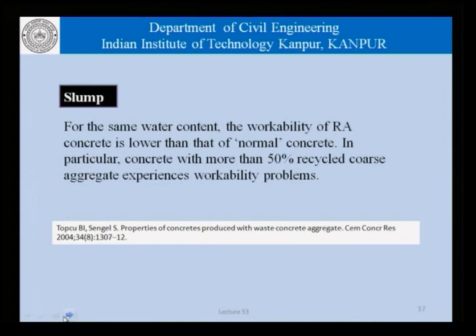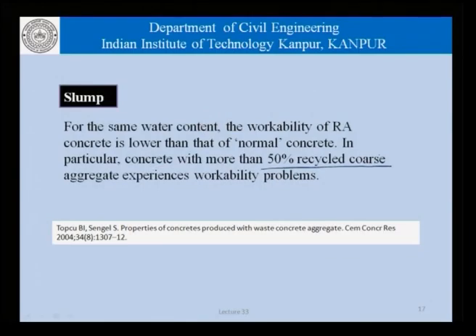As far as the slump, that is the workability, of concrete made with recycled aggregates is concerned, for the same water content, the workability of recycled aggregate concrete is lower than that of normal concrete, that is concrete made with normal aggregates. In particular, concretes with more than 50% recycled coarse aggregate experience workability related issues. So, for the first time today, we are talking in terms of 50% recycled coarse aggregate.